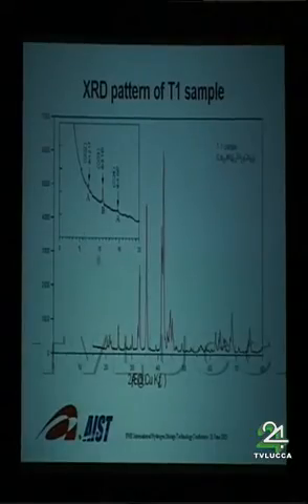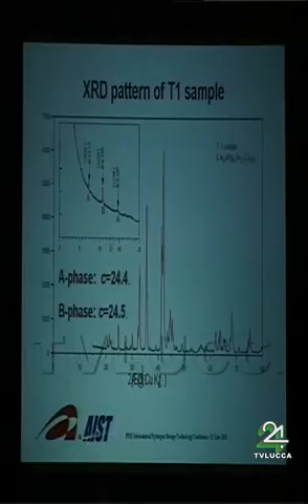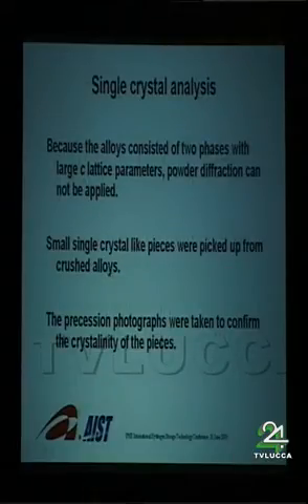If we look at the very low theta region, we found two phases with very large lattice parameters. One phase has 24.4 angstrom, and the other phase has 24.5 angstrom. So it's very difficult to use the powder diffraction method or Rietveld analysis to distinguish two phases and determine their crystal structure. So we moved to single crystal analysis, because the alloys consist of two phases with large lattice parameters. Powder diffraction cannot be applied.